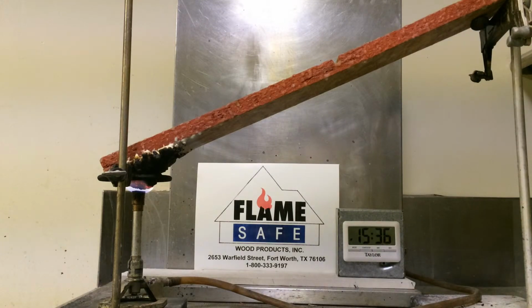And on OSB, it also meets the qualifications for a FRT rating, which means it can be used as air chases. The requirement for an air chase has to do with the smoke development index. FlameSafe Fire Poly, when applied to OSB and tested according to the ASTM E84, had a smoke index rating of 40, which is substantially less than what the requirement is.